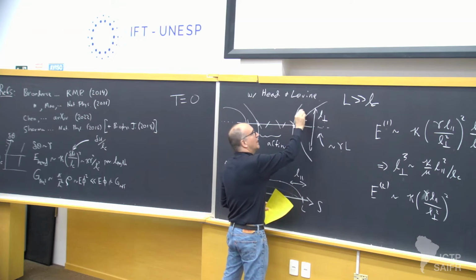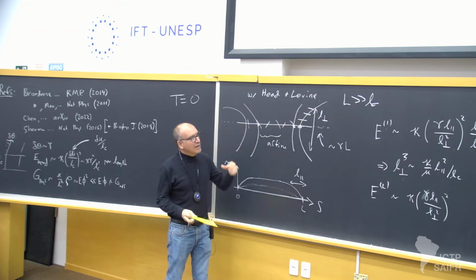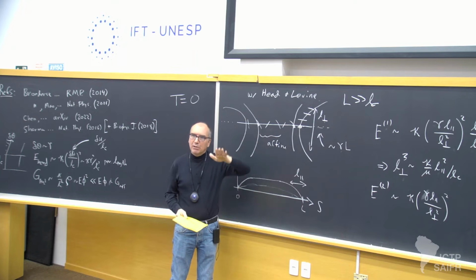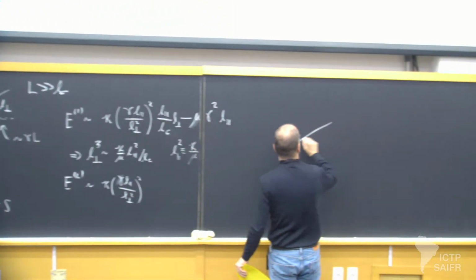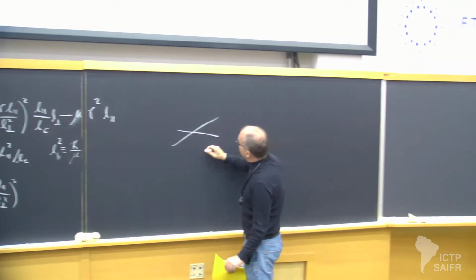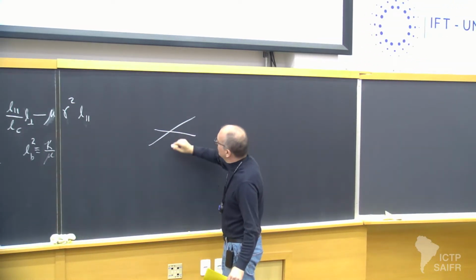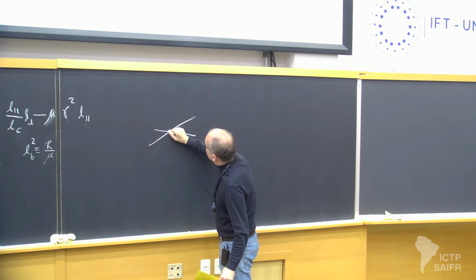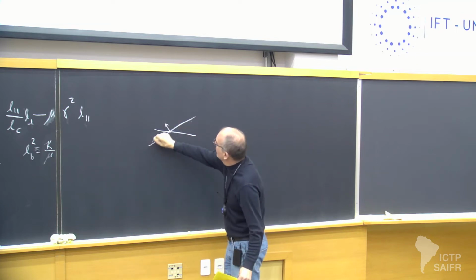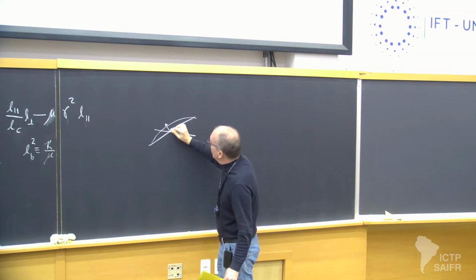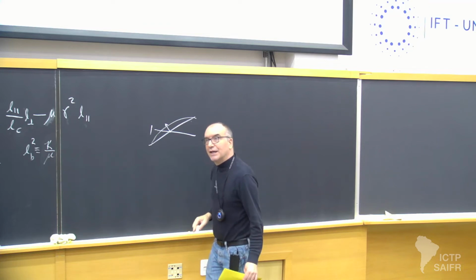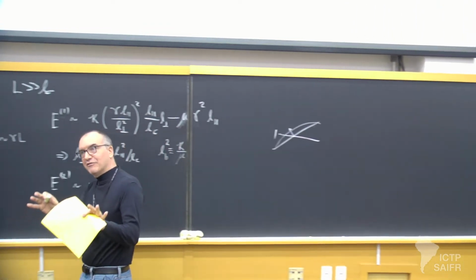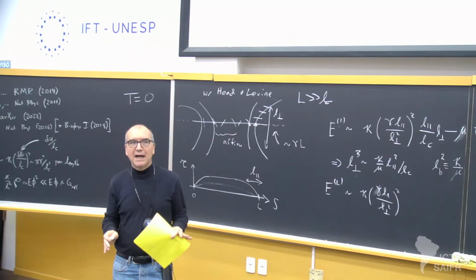What are those filaments? Well, they're filaments that are crossing at not 90 degrees to that, but at a typical large angle on average, right? Now, in 2 dimensions, this is one key observation about 2 dimensions, even if I cross at some odd angle, I can't just displace this node perpendicular to this filament in order to generate a bend. I can't do that without compressing this filament segment because it's connected to something else. Now, this is relating to the isostatic condition of Maxwell, which you've heard about, right? And I'll remind you of that in a moment.